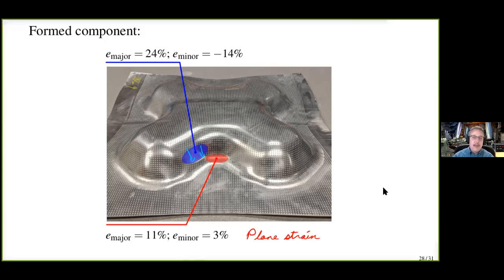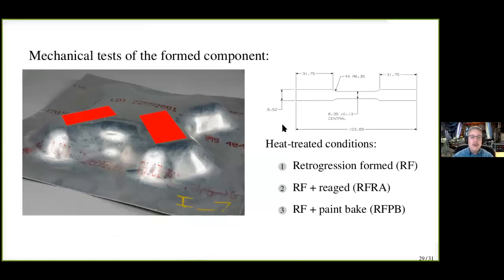So after forming, it's retrogression formed. We need to reage it to get the strength. So we took some sheets that were formed, cut out specimens here and here after we subjected this material to reaging. So we tested as formed or as retrogression formed plus our full reage, and retrogression formed plus a paint bake. And we used the standard ASTM E8 specimens for this, like sub-size specimens actually.